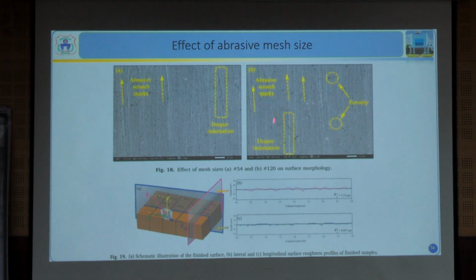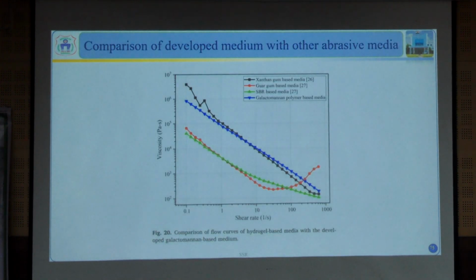The abrasive size is also proved with SEM images, showing what kind of abrasive size is used, abrasive scratch marks, deeper indentations, and if any porosity is observed on the finished surface. These were identified, and media were developed and compared with other media.